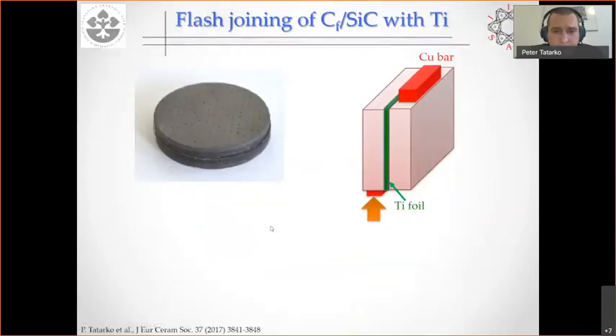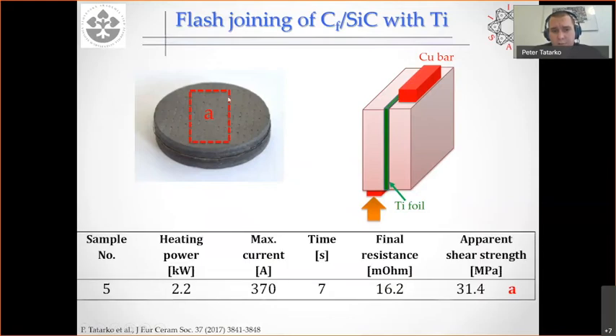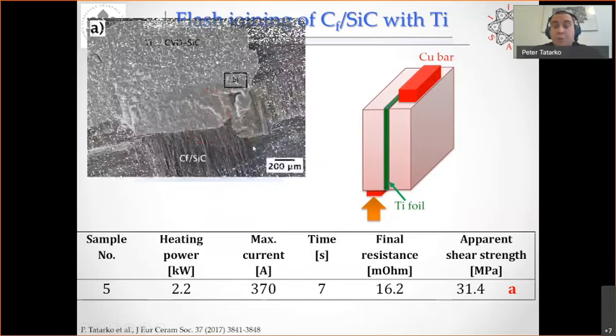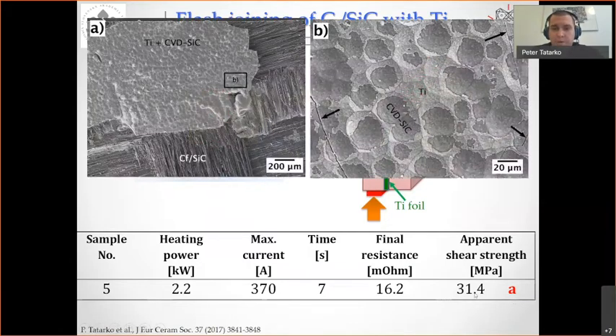So after joining, of course, after understanding the temperature in there and what you have in the joining area, you always need to know the strength, the mechanical performance of the joint. So we cut the sample right from the middle, and here you can see that we got an apparent shear strength of about 31.4 megapascal, which is an extremely high value, and we reached the value of the reference unjoined material. I will show very soon the comparison with the other process.